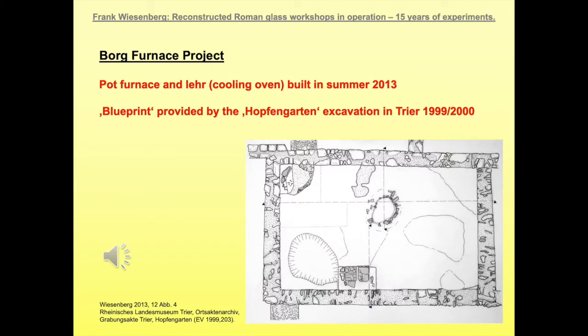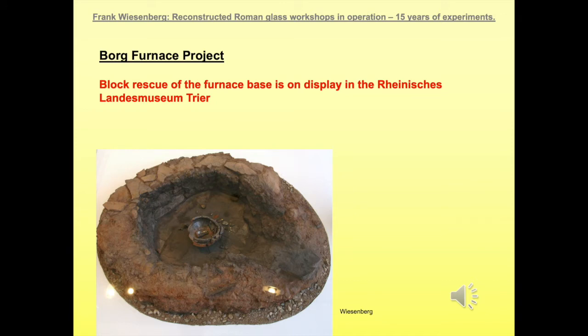At Borg, apart from the furnace fragments, no remains of the glass furnace were excavated, so there's no evidence for the exact location of the glass furnace, nor is there any evidence for the layout of the glass furnace itself. So the blueprint of the glass workshop, which was reconstructed at the Villa Borg, was taken from the Hopfengarten excavation in Trier, which is quite close by, actually 30 kilometers from Borg. This excavation in Trier features a very small glass furnace, with a fire pit diameter of just 55 centimeters, and another structure pretty close by, which very possibly is or was an annealing oven. The furnace base of the Hopfengarten glass furnace is still on display in the Rheinisches Landesmuseum in Trier as a block rescue.